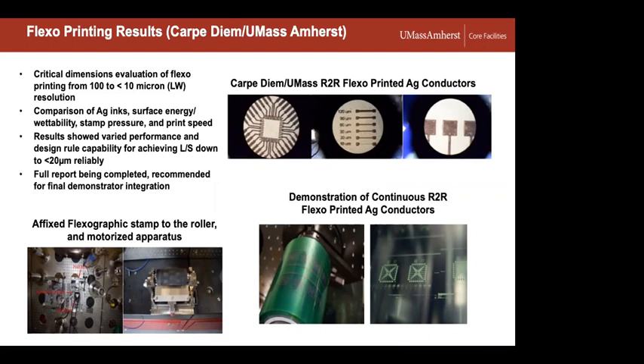So this is some example of flexographic printing. It's a little bit different in that you basically take a stamp, you wet that with an ink using another technique or a rod, which basically picks that ink up out of a well. It wets that pattern that you have on a stamp, and then the stamp just puts it down on your substrate. Again, that's how newspapers were originally printed. Now we're looking at silver inks and other ink materials.